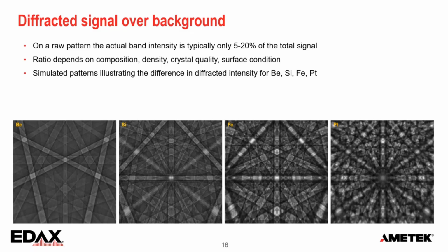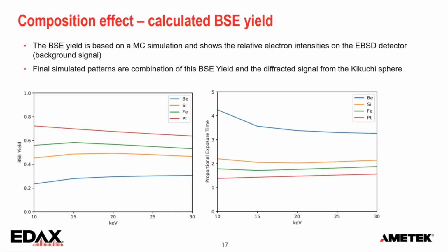You can also see that when we just do a simulation on the diffracted signal. So this is not taking into account the background intensity. And then from beryllium, you can see that the contrast really increases when you go to heavier materials. So this is really what happens. And we can quantify that in the calculated backscatter yield. And when you look here on the left, platinum, iron, silicon, beryllium, when you go to high KV, beryllium has the lowest yields, and then platinum, iron, etc. are a little bit higher.